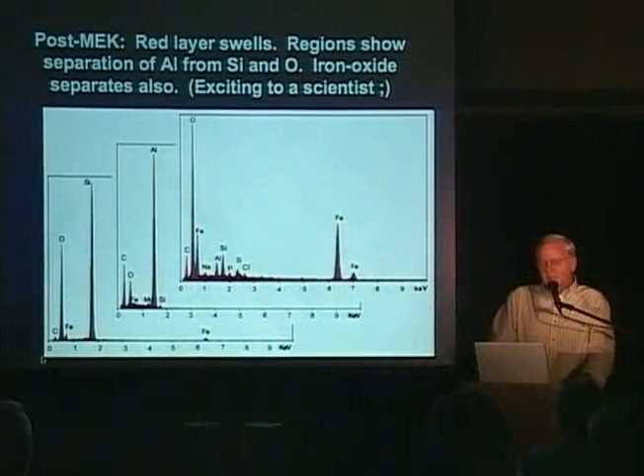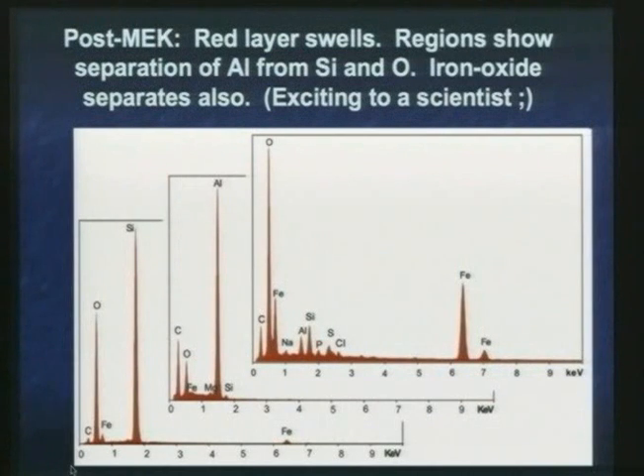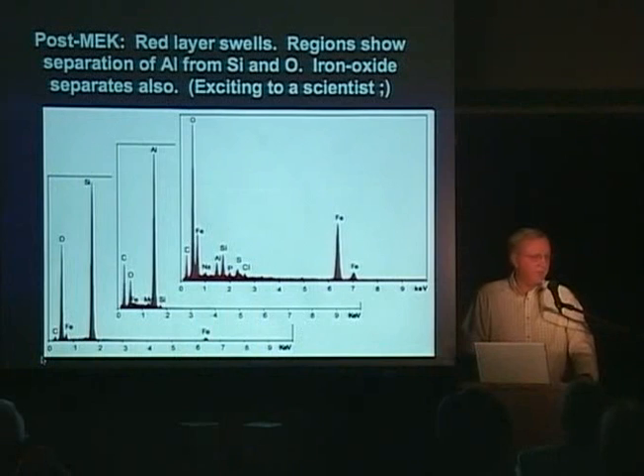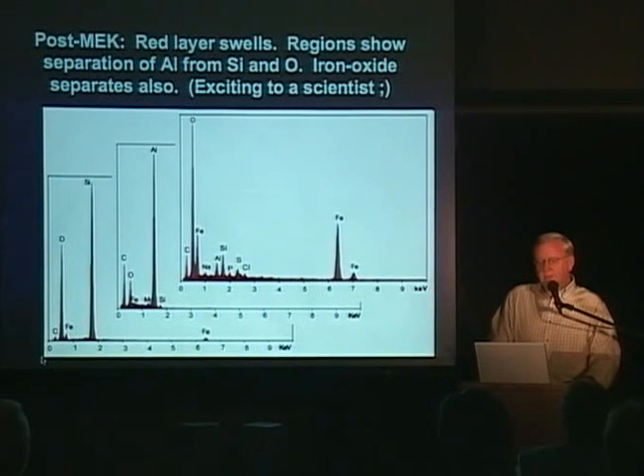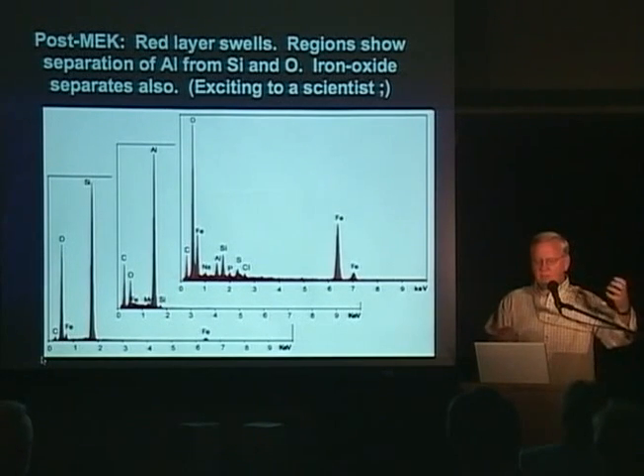Now if you look at the middle plot, you see a large peak of aluminum, very little silicon. Again, this is not an aluminosilicate because the aluminum has now increased dramatically, pulled out of this matrix of stuff in the red material. The oxygen is much less than the aluminum, and we deduced, Dr. Fair is an expert in this machine, that the aluminum content exceeds the oxygen content significantly, and so there must be at least some elemental aluminum, which is one of the prime ingredients of thermite. There is also iron oxide, as shown in the rightmost plot, oxygen and iron. Here, the oxygen in each case was sufficient to completely oxidize the iron, unlike the aluminum, where the oxygen was insufficient to oxidize all of the aluminum. See the difference? So elemental aluminum had to be present.